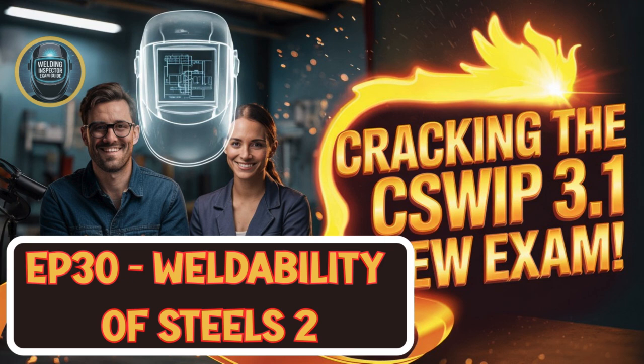That sounds incredibly useful. So what do typical CEV numbers mean in practice? Like, what precautions are needed? Okay, let's break it down based on typical ranges. For common mild steel, the CEV is usually less than 0.4. These steels are considered readily weldable. You generally don't need to preheat the metal before welding if you're using what we call low hydrogen welding processes.